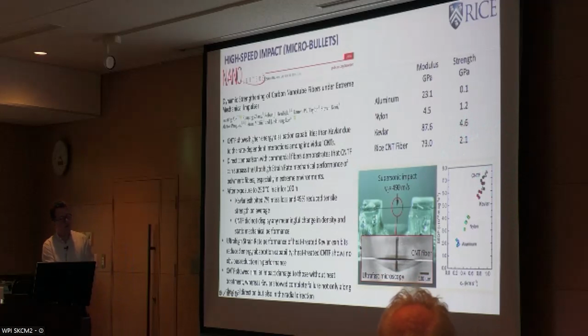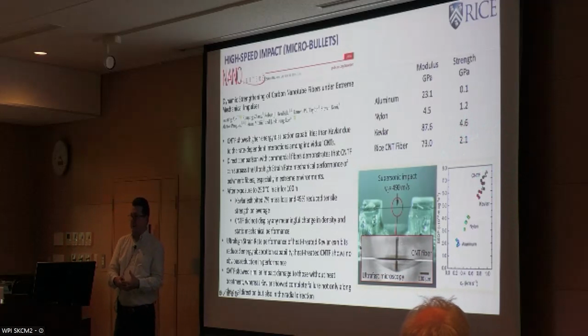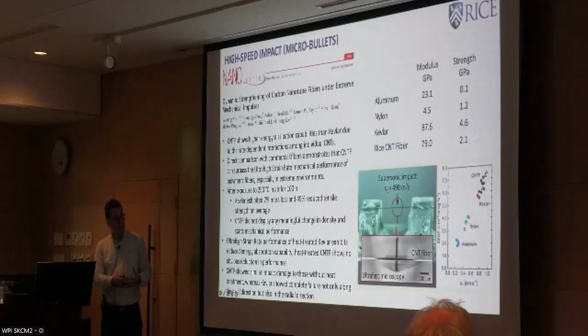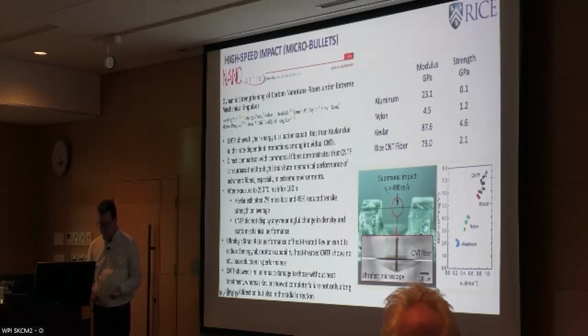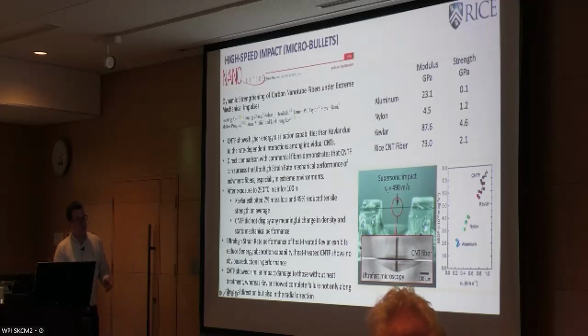And the reason is that these fibers hold together by weak forces that are rate dependent, right? So when you pull them quasi-statically, you can actually pull them out more easily. When you hit them at very high speed, at some point, the dynamic friction is so high that you start breaking bonds. So in this case, we actually saw evidence of bond breaking in the impact structure.